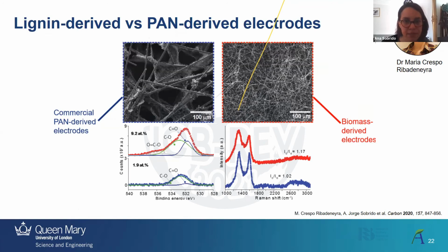Here we can see the lignin fibers compared to the commercial ones. This is the same scale bar, and you can see how much bigger the commercial fibers are. They also have some carbon additive to increase the electronic conductivity of the fibers. One thing that we were really pleased with, this is XPS, is that our fibers, the red being the biomass ones, had a much higher number of oxygen functional groups on the surface. This is quite important for the flow batteries, because the vanadium seems to attach to the oxygen functionalities on the surface to do the electron transfer and the reaction. So this is going to be quite key, and we're really pleased with that.